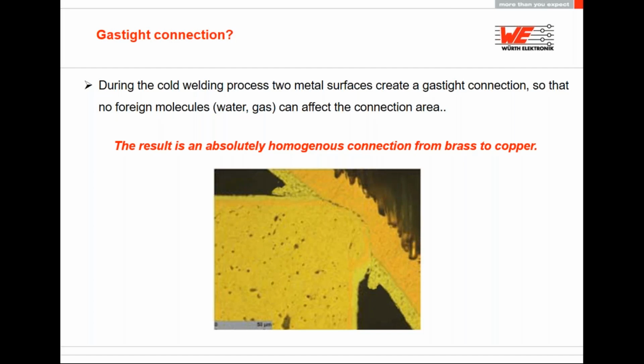So during the cold welding process, the junction between the brass of the power element and the copper of the via becomes an absolutely homogeneous and gas-tight connection, which has a very low contact resistance and high mechanical retention force. The pin surface provides a smooth sliding into the via and is pressed to the sides, creating an additional sealing around the connection.